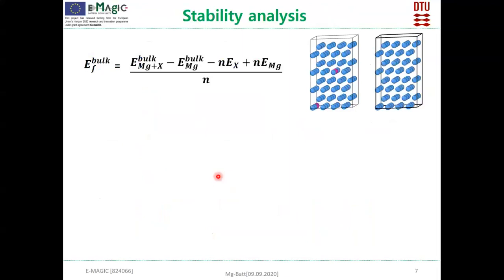And the next step is to check whether the alloy is stable. So this is calculated based on the energy of formation with the dopant in the bulk, and it is calculated using this equation. The first term indicates the energy of the structure with the dopant, and then the energy of the structure without a dopant, and Ex is the energy of the dopant in its ground state, and Emg is the energy per atom of the pure magnesium, and thus we obtain the bulk energy of formation.